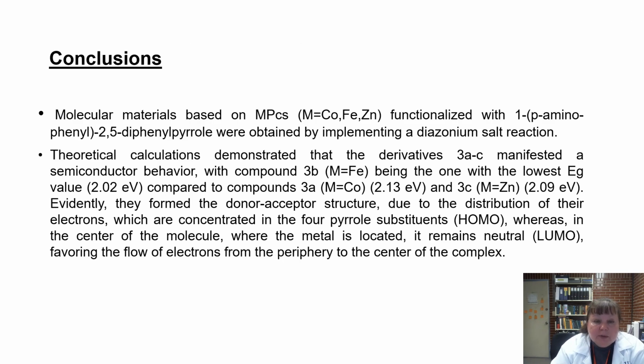Conclusions. Molecular materials based on metallophthalocyanines with metal center cobalt, iron, and zinc functionalized with 1-para-aminophenyl-2,5-diphenylpyrrole were obtained by implementing a diazonium salt reaction. Theoretical calculations demonstrated that the derivatives 3A, B, C manifested a semiconductor behavior with compound 3B, metal center iron, being the one with the lowest Eg value, 2.02 electron volts, compared to compounds 3A and 3C, metal center cobalt and metal center zinc, respectively.